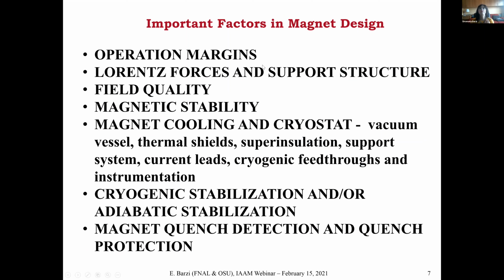And there are a lot of other factors that are important. Like if you want to use the magnet in an accelerator, the performance has to exceed the nominal performance in the machine, because you want to have some margin during operation. Then I mentioned the mechanical forces, the support structure, and now actually this is our bottleneck, because the materials, stainless steel, Inconel, and the conductor itself especially, cannot take more than some megapascal of pressure, and after that, the yield stress, we are going very much beyond the yield stress of the superconductor and the structure material. So that's where we are. The bottleneck now is not in the current capabilities, but in the mechanical features of these materials. And then I mentioned field quality and magnetic stability, which are important to show you how we improve this wire.